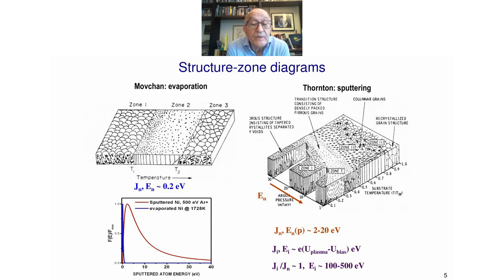We again have the homologous temperature, but he added a gas pressure axis extending from 1 to like 30 or 40 millitorr. In the high pressure range on the top side, the particles are thermalized, so the Thornton diagram is identical to the Movchan diagram. But as the pressure is lower, we preserve the high energy of the sputtered particles. Thornton also pays a lot of attention to the ions backscattered from the target, which is a big flux, especially for heavy targets, that bombards the substrate and produces this transition zone, which has bulk-like properties, but also stresses.